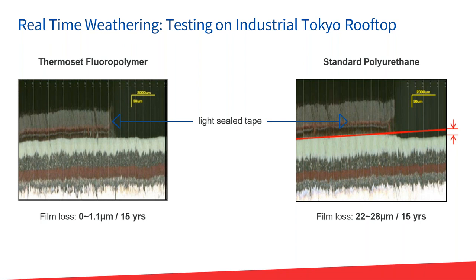And that is actually a light sealed tape. So under that is an area of paint that's protected from UV light, and just adjacent to that is what was exposed. You can see that comparing the two, the exposed area did lose about 1 mil to basic erosion from UV light and salts and moisture over about 15 years.